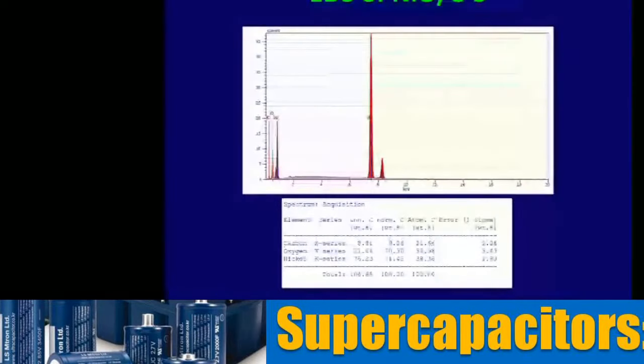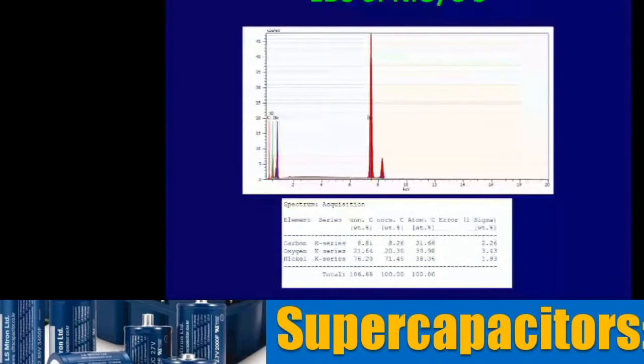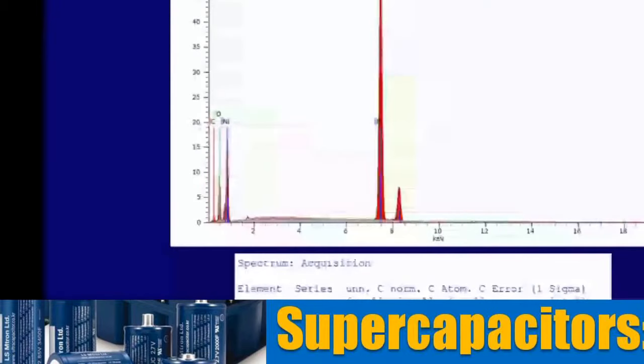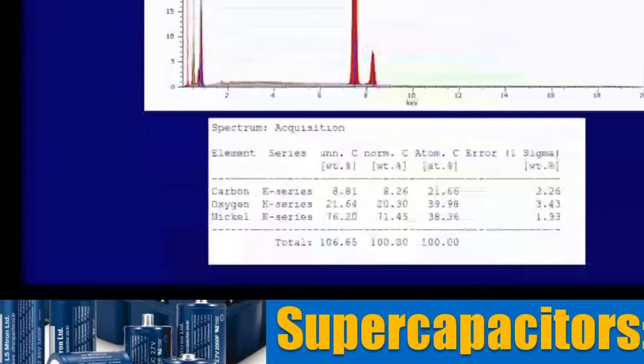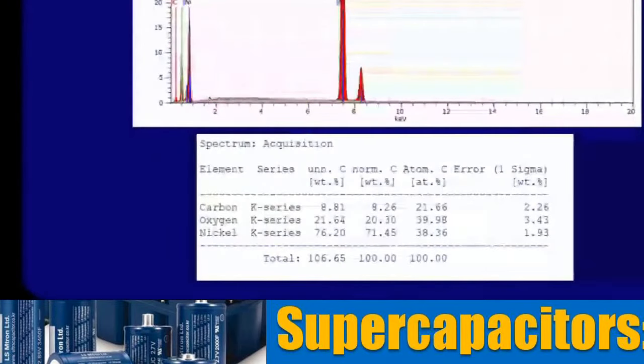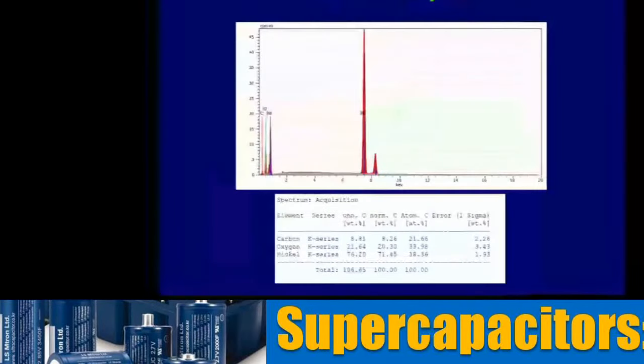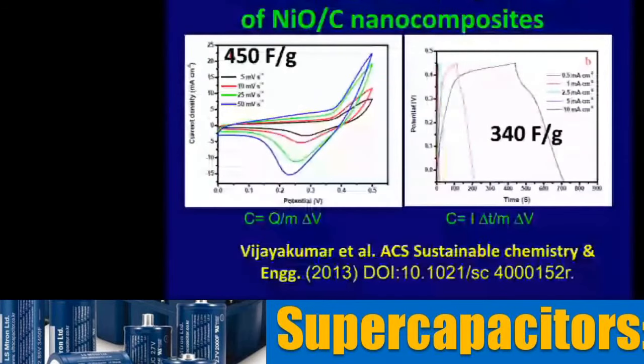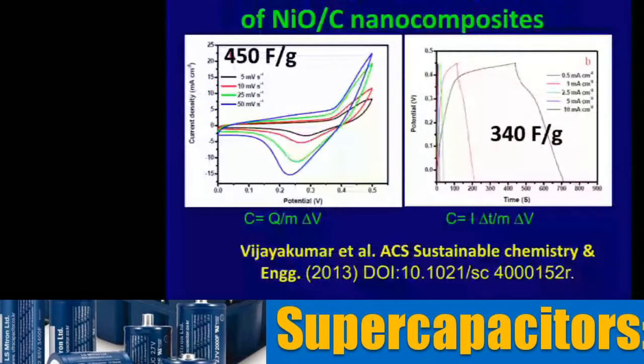Not only that, because we say carbon is available, it's essential to identify whether carbon is really present. To do that, we go for energy dispersive analysis, or EDAX, and you can see the EDAX spectrum here. You see the atomic percentage and mass percentage of carbon and nickel in it, which confirms that carbon is there, because when we treat at 600 degrees, there is a chance that part of the carbon can escape the material. In a similar manner, we have made measurements. You can see that we get about 450 farad per gram.